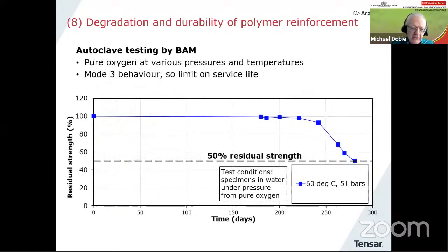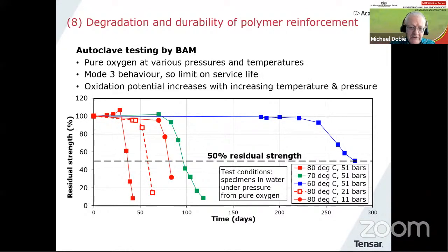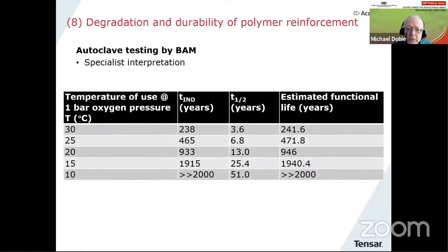And here's a typical result. So you see residual strength on the vertical axis versus the time of exposure inside the autoclave on the horizontal axis. And you can see that mode 3 behavior very clearly. So up to about 220 days, no loss of strength, but then it suddenly drops off. That's at 60 degrees centigrade and 51 bars. The green data is for 70 and the red data is for 80 degrees. And from interpretation of this, which is a fairly specialist thing, we don't come up with reduction factors, we come up with design life. And you can see there, even at 30 centigrade for this particular material, it is pretty high, almost 250 years predicted design life in terms of oxidation.